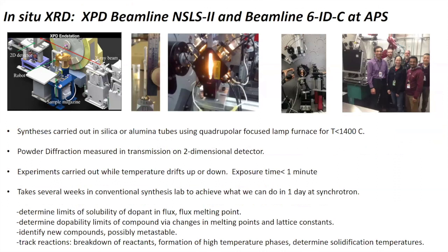So here's a picture of the experimental setup. Essentially, we have these alumina crucibles where the reactions are going to take place. Because X-rays have to penetrate the alumina, we need to use high energy X-rays above 10 keV. And this is a picture of the XPD beamline at the NSLS2 synchrotron. The X-rays come from the right, indicated by this red line. The sample is placed here at the scattering center, and the diffraction pattern is collected over here on this 2D detector. The sample is going to be warmed by this focused lamp, and we can control the temperature carefully.